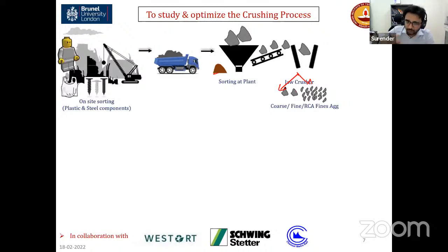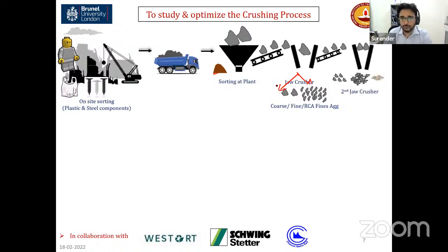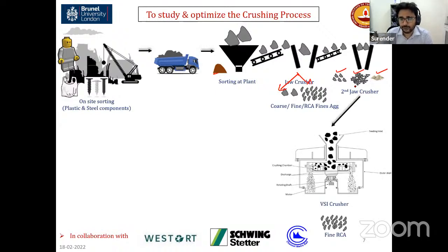And what we have seen in India is that now we have two-stage crushing, right? One jaw crusher after the other jaw crusher, so that the size reduction could be significant. Then, apart from coarse aggregate and fine aggregate, we can also get the concrete fines. Right now we are exploring how to use these recycled concrete fines, because maybe they can be used for cement regeneration, right? They can be used for carbon sequestration, as Dr. Sean mentioned. And nowadays, the most advanced facilities also keep one more crusher, the vertical shaft impact crusher, VSI, for enhancing the morphological properties of fine aggregates.